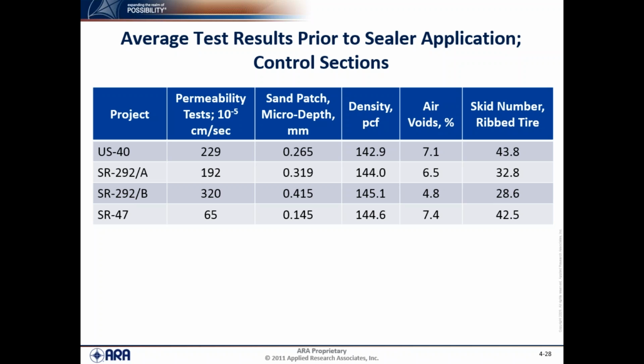And this is the corresponding air voids in percent. Again, the 292B had lower air voids, higher densities, which you kind of expect. The US 40 had the lower density and about the highest air voids. But they're all still very good. You know, I don't want to say high or low. All these values in terms of original conditions would represent a good material. And these are the skid numbers of the control sections prior to sealer application.